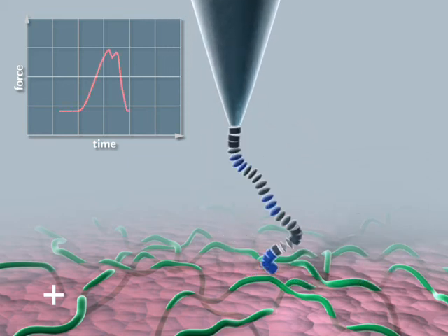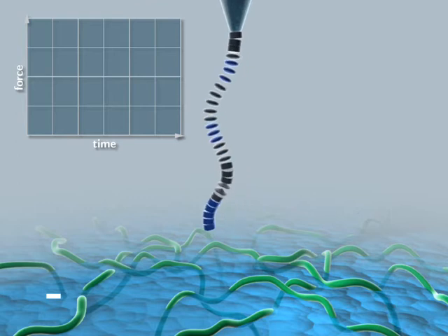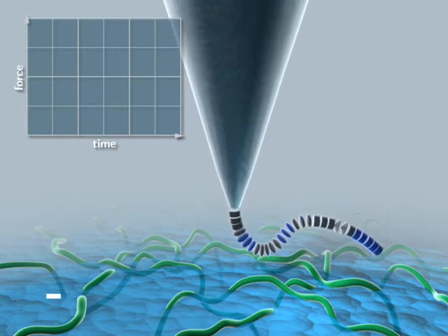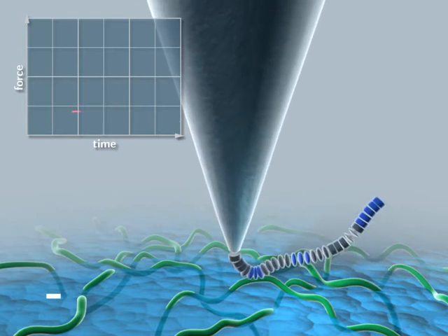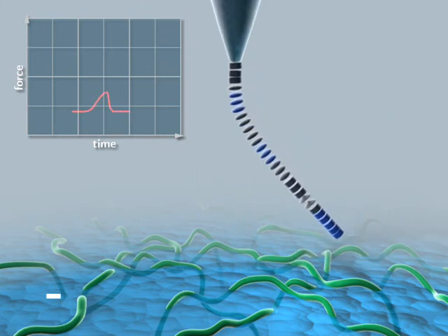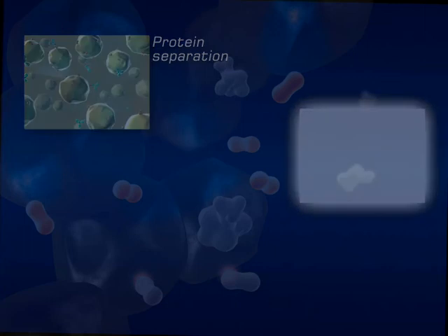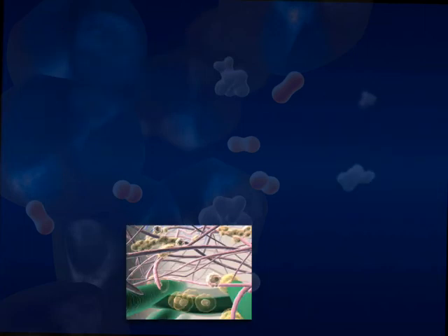We can bring the molecule of interest into contact with an organic conducting polymer surface, and then apply different electrical potentials. Here we see that on changing the electrical potential, the force required to remove the biomolecule of interest is greatly affected. Over the past 2 decades, using various experimental approaches, we have gained insights into our ability to control complex biomolecular interactions using conducting polymers.